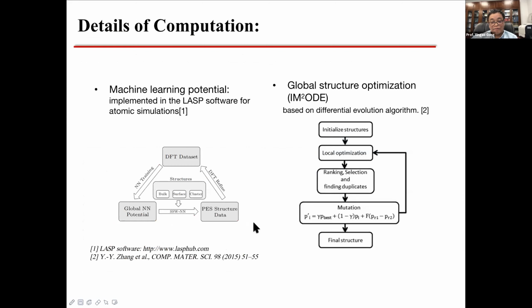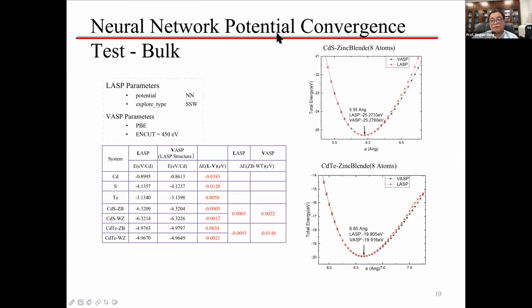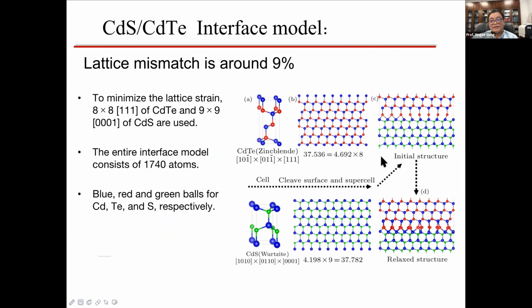So we build this potential for these systems, for cadmium telluride and cadmium sulfide, and compare it to real VASP first principle calculations. You can see the total energy difference is very small. That means this kind of potential can be very good for these systems. So the point is how to build an interface model for the simulations. As I told you, the systems have a very large lattice mismatch, and that means they cannot simply be put together. So we built a model.